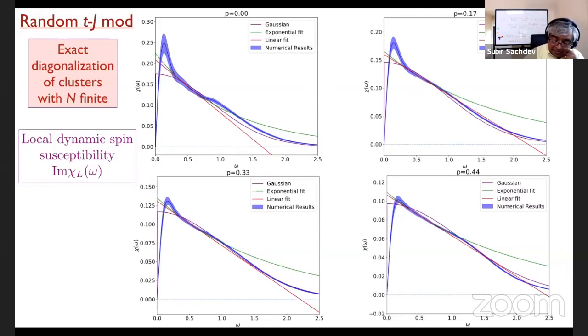But what does happen when you increase the doping, and this is the new result, is that the spin glass order disappears. This is already 0.01, where this is not very significant, but around 1/3, maybe a bit above 1/3, and above this, you don't have spin glass order at all. So there seems to be some critical point near 1/3 where the spin glass order disappears, and that's very much in accord with the very simple argument I gave for the 1/3 point. That's the point where the spinon and the holon states have the same energy, and that's where you expect the critical point in these models, near there.